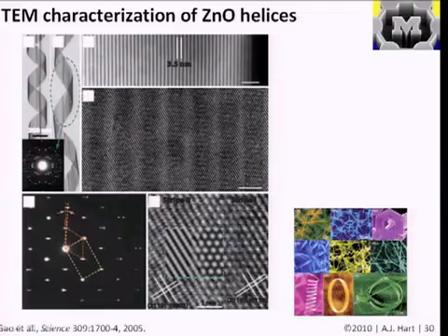So I don't recall what crystal structures these are, but you see this striping from one domain to the other, and you can actually resolve the atomic interface, and you can see that the orientation of the lattice is different, and they suggest that in the synthesis process, whatever drives that change or the formation of that domain boundary is what then causes the twist, because these bands then stack up into, you could say, a sub-micron scale twist resulting from this atomic interface behavior.